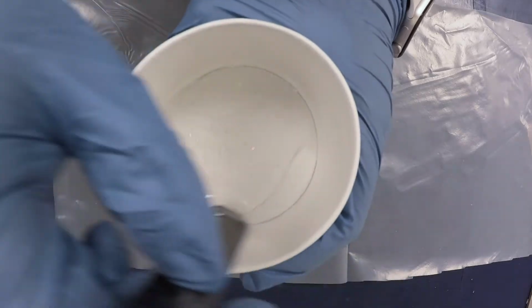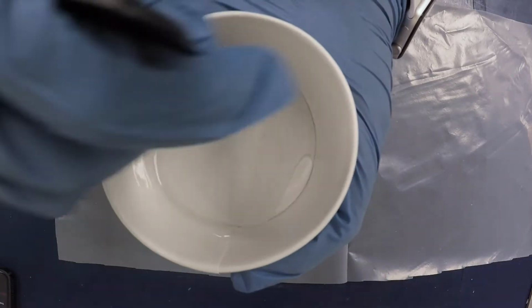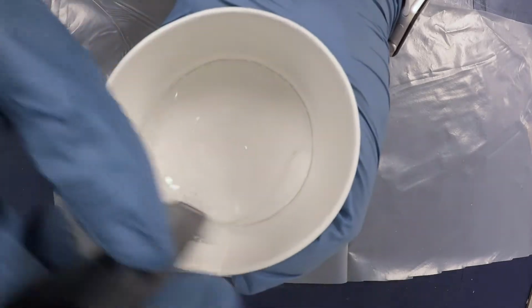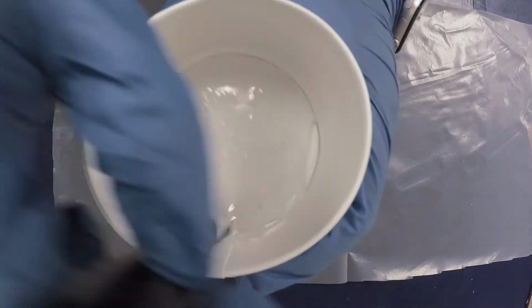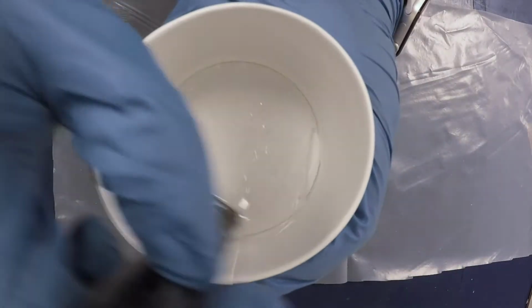Keep in mind that epoxy will have different mixing ratios, whether by weight or by volume. If this ratio is not accurately followed, the resulting matrix will fail. Always read the specified directions on your epoxy datasheet.